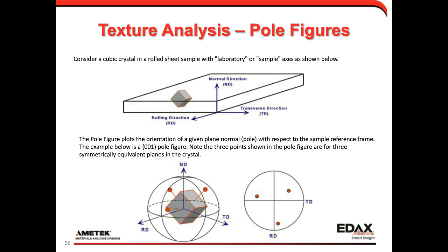And so when we show a pole figure, we look at the distribution of a specific crystallographic pole. In this little schematic, we're showing the 100 faces of a cube. We put the cube in the center of our measurement reference frame. We show where those poles are on the surface of a sphere, but then we take that three-dimensional sphere and convert it to a two-dimensional projection to show that as a pole figure. So we see where those poles are located in sample space. We can see where those three poles are, and we can look at the top hemisphere, the bottom hemisphere. But with magnesium, we're going to generally look at the 001 or the basal pole distribution.